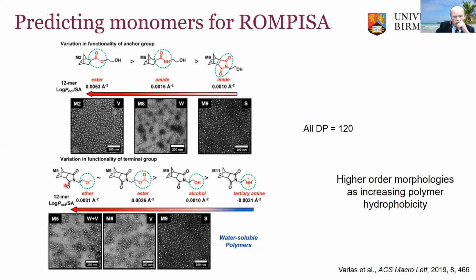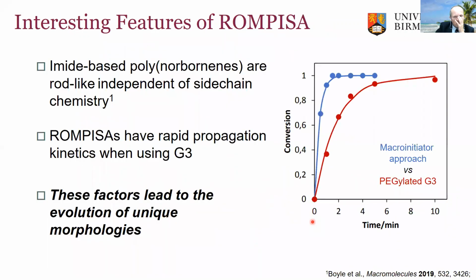If you look at the dependent functional group and how that affects the morphology formed, we see a very similar trend again, where we get higher order morphologies as we increase polymer hydrophobicity. So this helps us plan our phase diagrams and plan some of our targeted DPs a little bit better. One of the interesting features of ROMP PISA was that these imide-based polynorbornenes have quite a rod-like structure. This is independent of the side chain chemistry, but they also have extremely fast propagation kinetics.